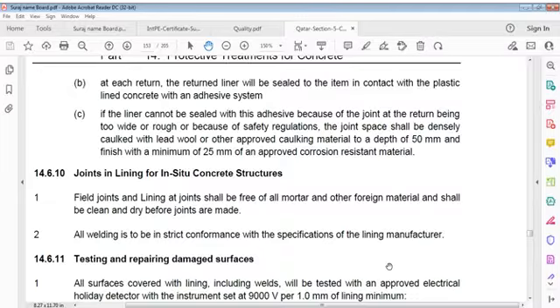If liner cannot be sealed with this adhesive because of joint at return being too wide or rough, or because of safety regulations, joint space shall be densely caulked with lead wool or other approved caulking material to a depth of 50 mm and finished with a minimum 25 mm.